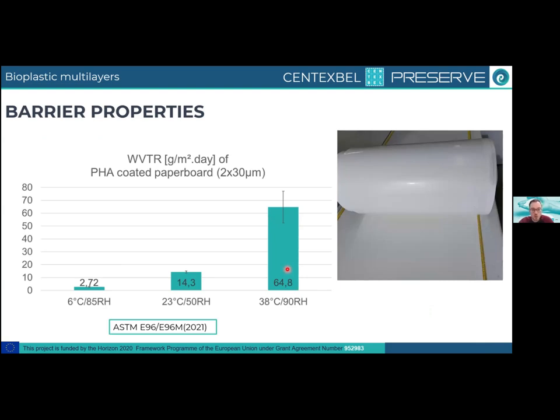Next, I want to show you the barrier properties. So I asked, can we reach this? This is a very big question. A fully bio-based material that has some high barrier properties. And here you can see the water vapor transmission rate of the PHA coated paperboard. So this is coated twice with each layer being 30 microns, very thin.